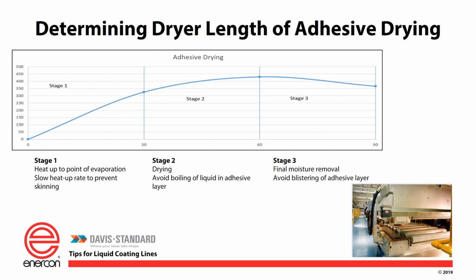I need to dry it down to a very finite dryness at the end, where it's usually less than 1% moisture left in there. But in here, stage 1 is where we're heating the web up and heating the coating up to get to the point of evaporation. Now, as a liquid evaporates, it actually creates a cooling effect. So in stage 1, we can put enough temperature to create all this and run it actually higher than we can in stage 2, because stage 2 is where you're actually drying with very little moisture left in there, so I don't have the same evaporative cooling. So now I've got to run maybe a little lower in my temperatures for that zone.